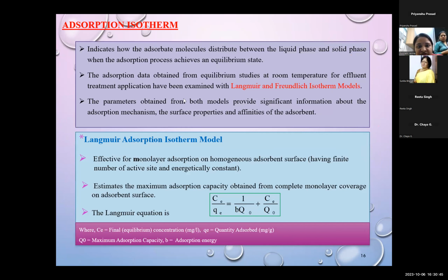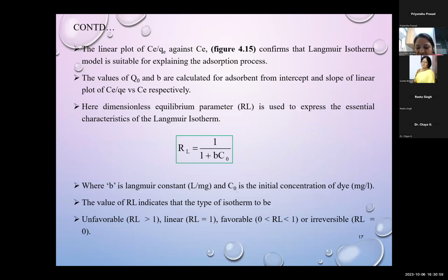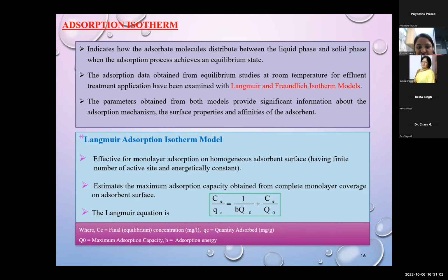Here the adsorption isotherms used are the Langmuir and Freundlich isotherm models, because they indicate how the adsorbate molecules distribute between the liquid phase and solid phase when the adsorption process achieves an equilibrium state. Langmuir adsorption shows effective monolayer adsorption on a homogeneous adsorbent surface having a finite number of active sites that are energetically constant. It also estimates the maximum adsorption capacity obtained from complete monolayer coverage on the adsorbent surface.